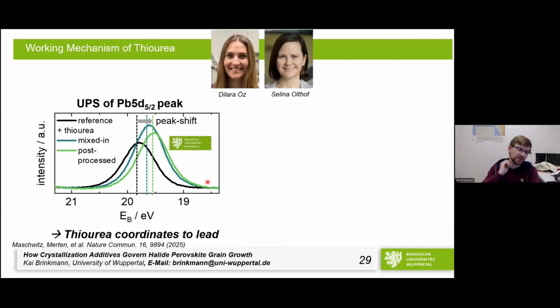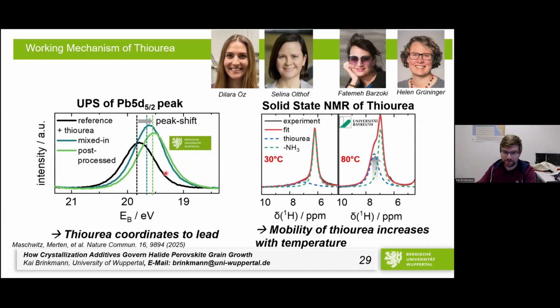Then we went on and had a little bit of a UPS measurement and looked at the chemical shifts. And indeed, the chemical shifts of the lead 5d also shifted if we expose the surface to thiourea. So we are pretty sure that the thiourea is sitting on the surface. And another thing that we investigated now again with Fatme and Helen is that we wanted to have a look what the thiourea is actually doing if we increase the temperature.